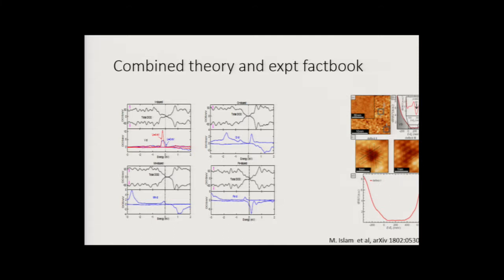So I would say that this is, to me at least, a very interesting example of knowing what the response of Dirac materials was in the case of the d-wave superconductor and graphene to defects. I can tell you it's very unlikely that there is a true gap in magnetically doped topological insulators. It is very unlikely that there is a gap. Put differently, the story about a magnetically induced gap in topological insulators is very likely subject to revision.